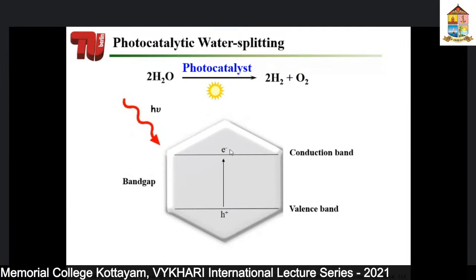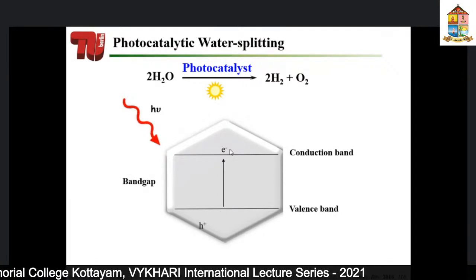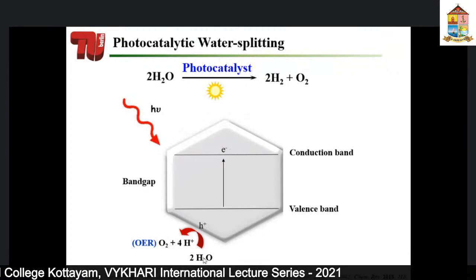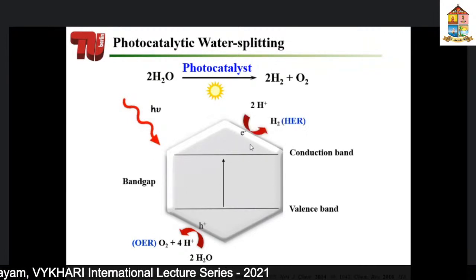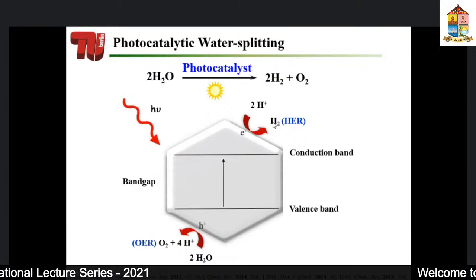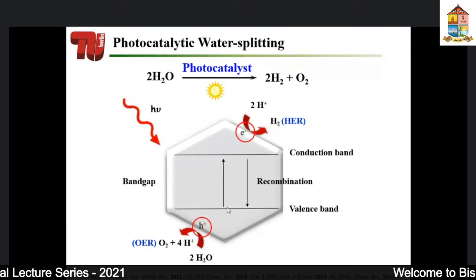What happens then is that the hole will move to the surface so as to oxidize water in the form of the oxygen evolution reaction. Similarly, the electron will move to the surface and reduce protons in the water to form hydrogen. So this is the hydrogen evolution reaction, and this is the oxygen evolution reaction, where you use holes, and here you use electrons. But there's a big problem here. When the electron hops from the valence band to the conduction band, it always wants to come back to the valence band. So the recombination rates for these reactions are very, very high.